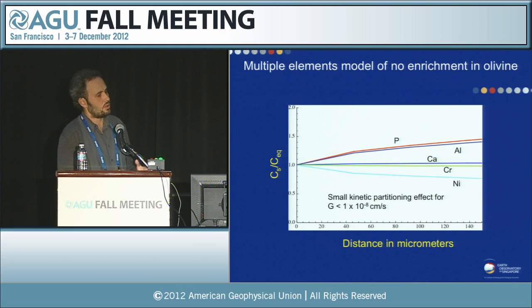A related calculation would be: what growth rates do we need if we don't want to have kinetic effects? So I say, look at my crystals, I believe nothing is affected by kinetics. When you say this, you are implying this kind of growth rate, which is about 2 or 3 orders of magnitude slower than the other one.